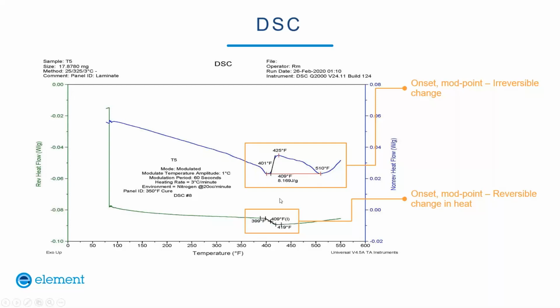And then the bottom curve is the reversible change of heat. And if you remember from the very beginning of the talk, we defined glass transition temperature as a reversible transition. In other words, you can go back and forth above and below the transition, and it will happen over and over again. Whereas a cure, it happens once and then it's done, it doesn't happen again. So in this case, we can clearly break out the onset, the midpoint, and the endpoint, and report them that way.